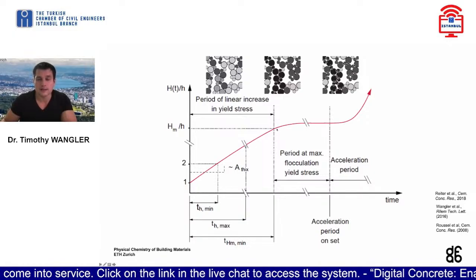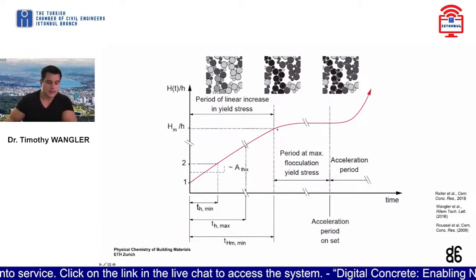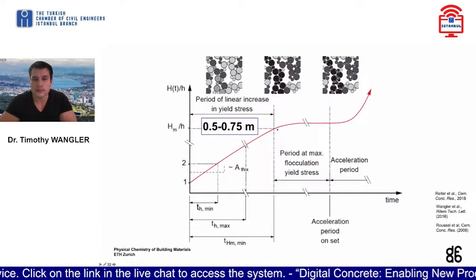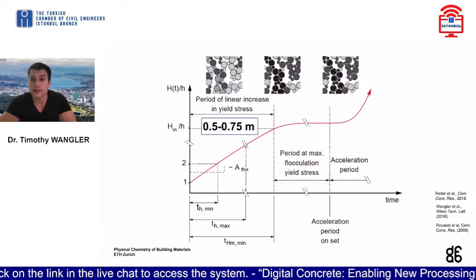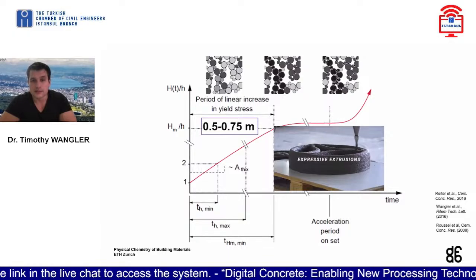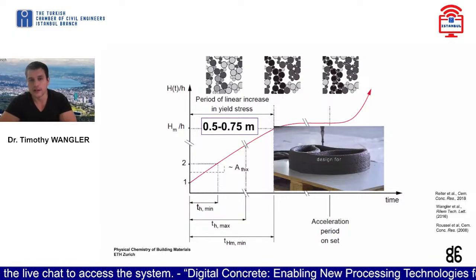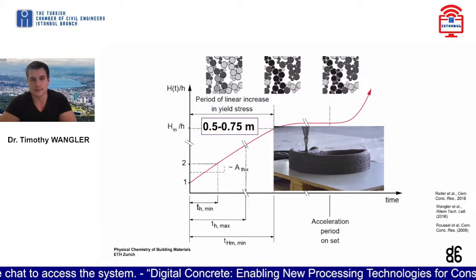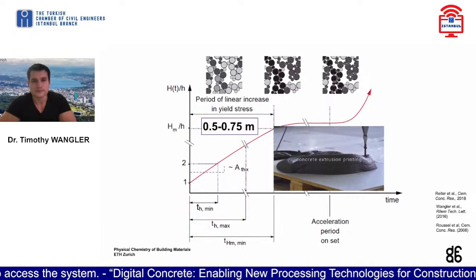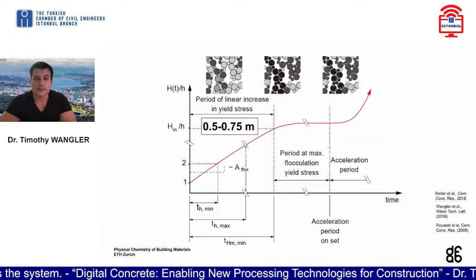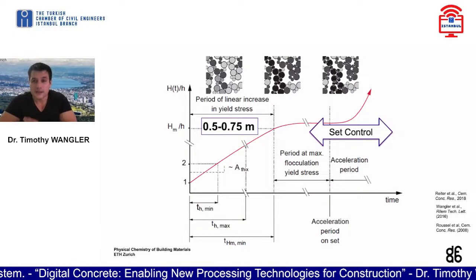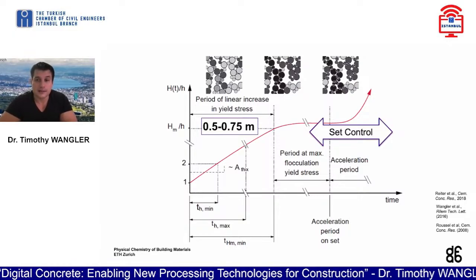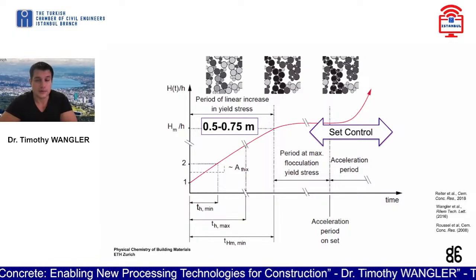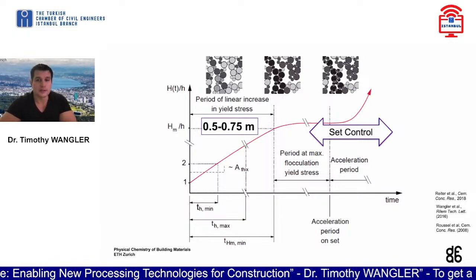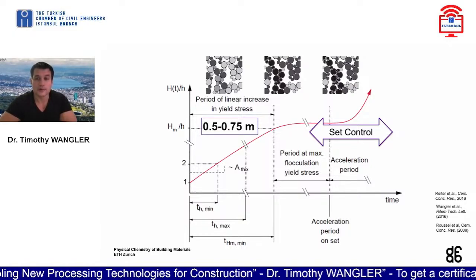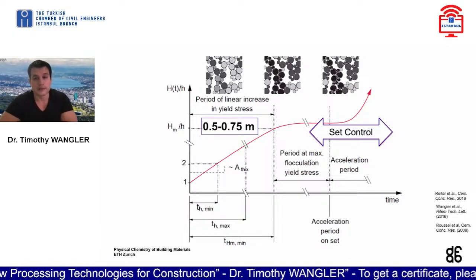If you rely on this, it normally reaches a limit, and this limit normally doesn't let you build much more than about 1/2 meter or 3/4 of a meter. And if you try to go above that limit, then you see what we see here with our more fluid concrete, so we don't get much more than 10 centimeters before it collapses. You get a collapse. So what that means then is that you have to initiate hydration, and to initiate hydration is some form of set control and the formation of massive hydration products, which then give you the strength buildup that you need. And this is done through the addition of an accelerator, typically.